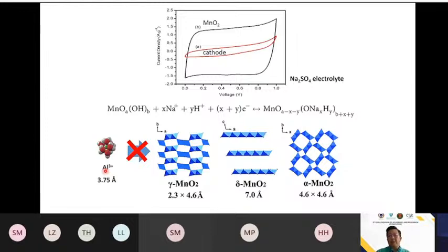We tried to use it on the aluminum electrolyte, but couldn't, because we looked at the pore size of the crystal void for this manganese oxide, and we found that it really couldn't trap, because it's too big. The void for this is too big to trap this aluminum ion.